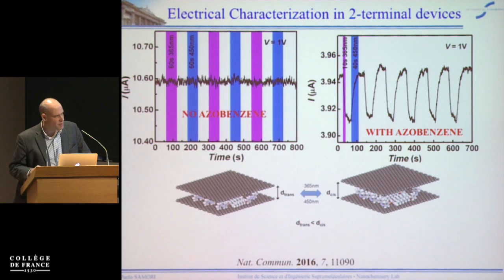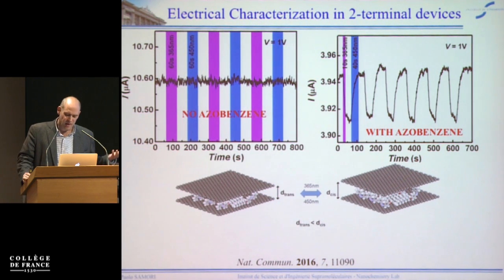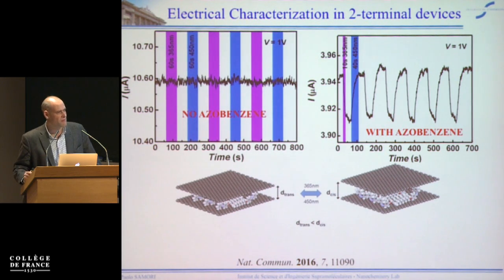Now, why does this happen? It happens because both modeling and X-ray diffraction showed us that the average distance between the adjacent layers is increasing, going from the trans to the cis. And so it's just the probability of the charge to hop from one to the adjacent layer. Now, you have to bear in mind that I showed you very nice images of the formation of lamellae of alkanes on the basal plane of graphene or graphite, but actually this was not really the case when we were doing sonication. So in situ during the sonication, you have to expect the molecules are quite disordered. But can we try to gain a higher degree of order of molecules on graphene and use this in order to confer some new properties to the graphene-based materials?